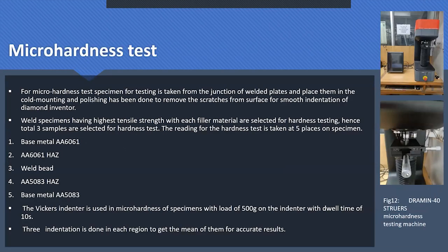Now coming to the micro hardness part, the specimen has been taken from the welded joint, which comprises 5 zones: 2 base metals, 2 heat affected zones, and 1 weld bead. The specimen has been cold mounted, and polishing has been done using different grades of waterproof sandpaper ranging from 100 to 2500. After the polishing is completed, the Vickers indenter is used for the micro hardness test with a load of 500 gram and a dwell time of 10 seconds. In total, 3 indents have been taken in each zone, so 15 indents on one specimen. At right, you can see the micro hardness testing machine, where the indenter is a Vickers hardness indenter.